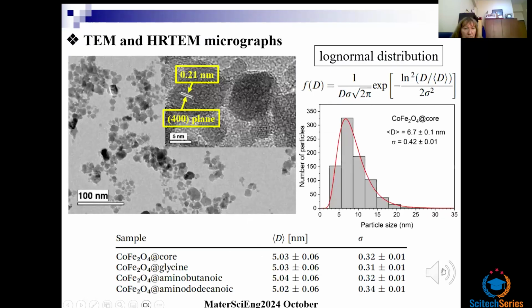This slide shows the transmission electron microscopy and the high resolution transmission electron microscopy of the as-precipitated nanoparticles. So from these micrographs, we can extract the particle size distribution, which is presented here on the right-hand side. There is the histogram. The vertical bars are the histogram, and the solid red line is the best fitting of this histogram using the log normal distribution function. And this is in particular the uncoated cobalt ferrite nanoparticles. So it's exactly the core of the nanoparticles.